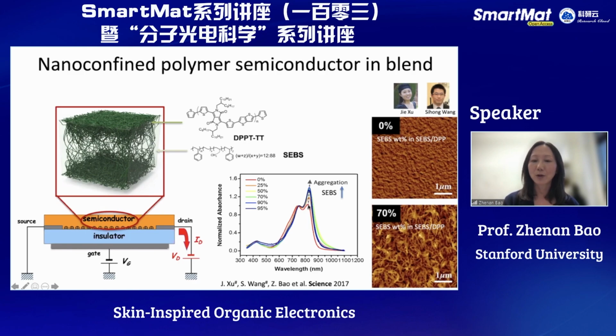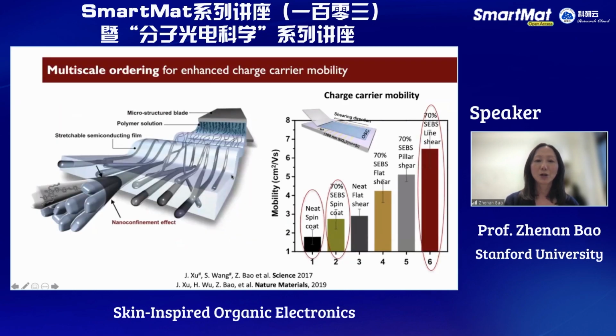indicating pre-aggregation formation. And then in the thin film, we see clearly these nanofibers that didn't exist in the original neat film. Pre-formation is important so that during the drying, these preformed networks can be connected together before the insulators start to get in between them. That's really the key for good charge transport.